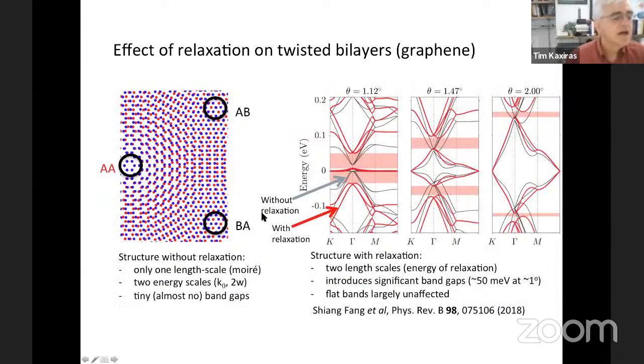Okay, so here's the real space again. Positions of atoms, blue and red layers in real space. And here are the bands in the reciprocal space. And again, the bands without relaxation are black. The bands with relaxation are red. And you see the gaps that appear here only when you include the relaxation. And without relaxation, there's essentially no gaps. However, interestingly enough, the shape of the bands does not change very much with relaxation. It's just that the bands shift and produce these band gaps.